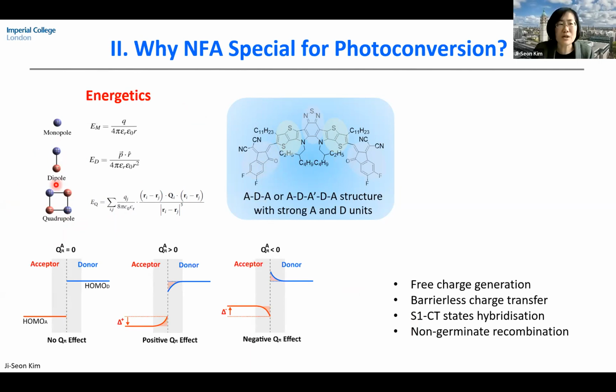Differently from dipole, the quadrupole case is a much shorter range electrostatic interaction because of the 1/r cube dependence of potential. So if you don't have any kind of quadrupole effect, you can draw your energy levels as a straight line, HOMO and LUMO. However, if a molecule has a positive quadrupole moment, it will pull down its energy levels. And if it has a negative quadrupole moment, it will push up its intrinsic energy levels.